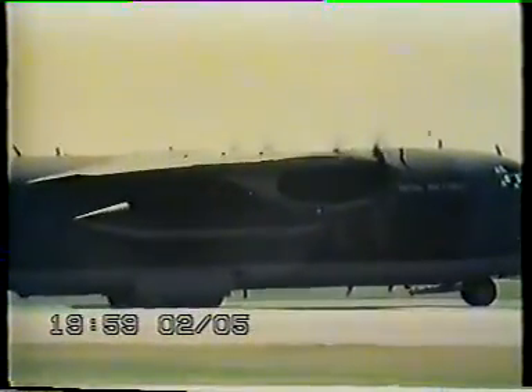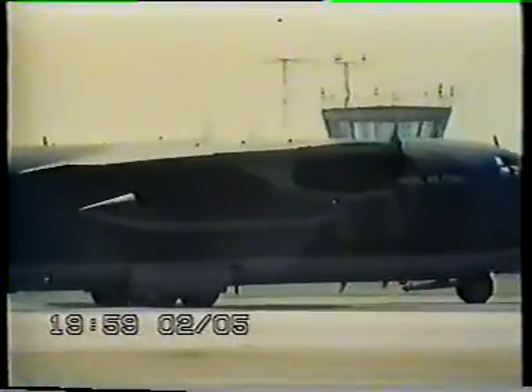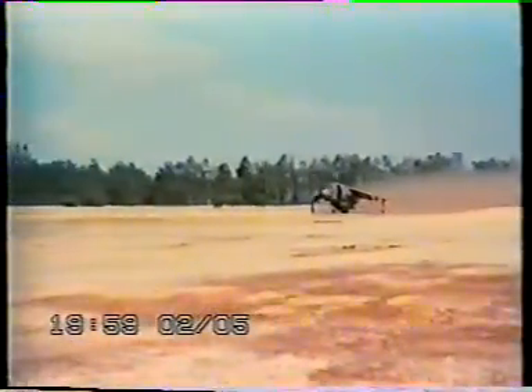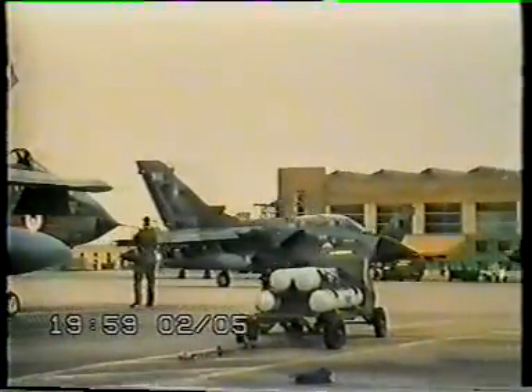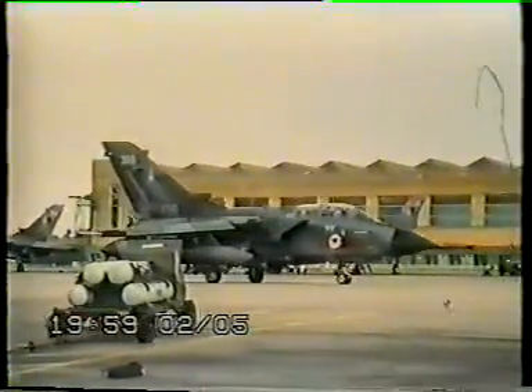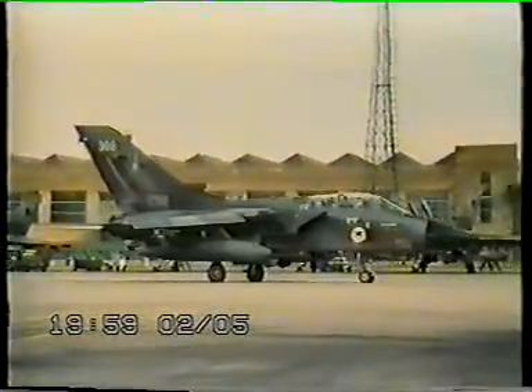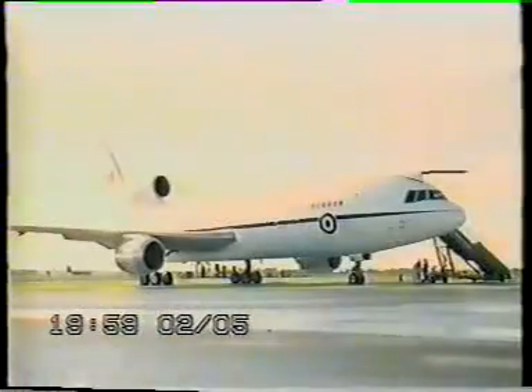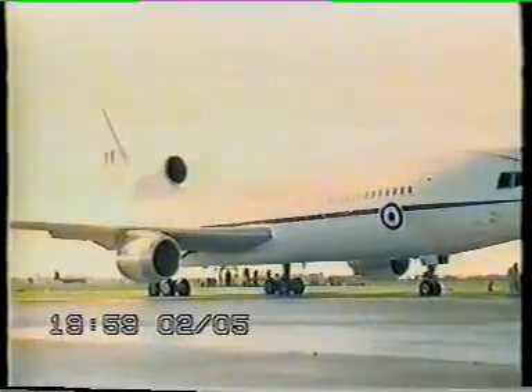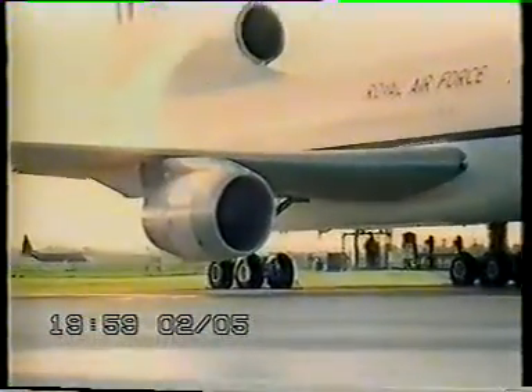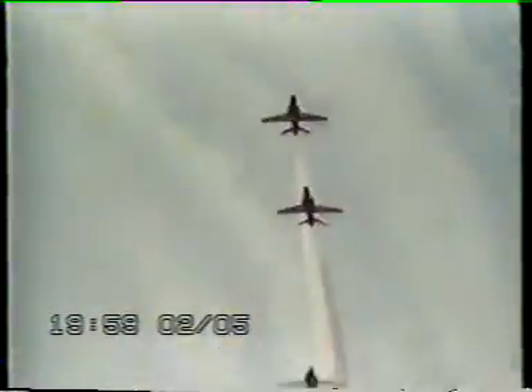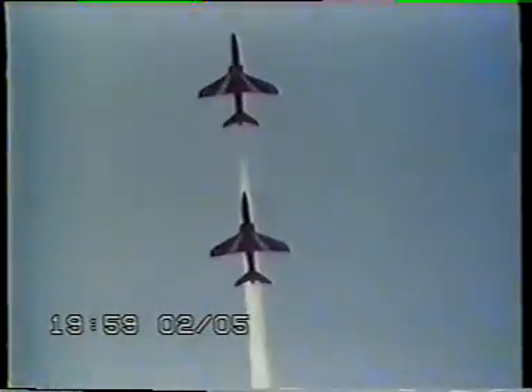Taxiing and towing also play a part. Even on a good taxiway, there will be some bouncing. Rough surfaces can cause very high stresses at the wing roots. The ground running of engines can have a significant effect on the airframe, and less obviously on the undercarriage. The engine itself suffers from fatigue. High cycle fatigue may affect blades or discs owing to internal dynamic effects. And there is the additional low cycle effect due to rotational stresses in response to changing engine settings.